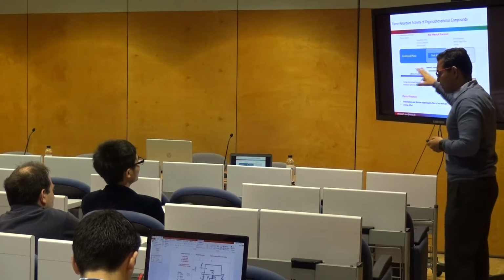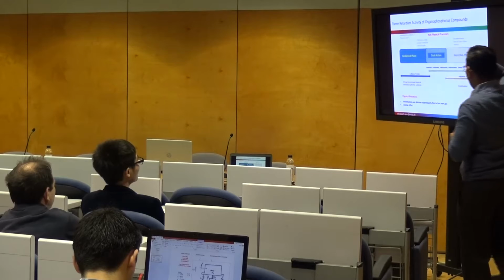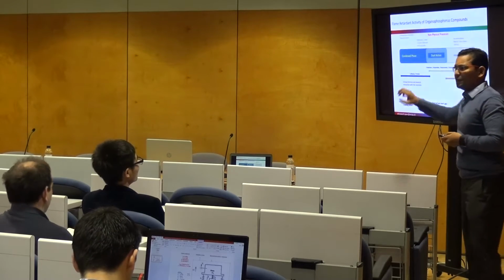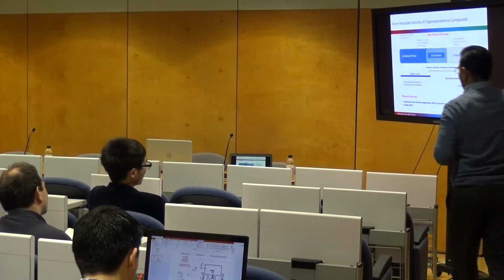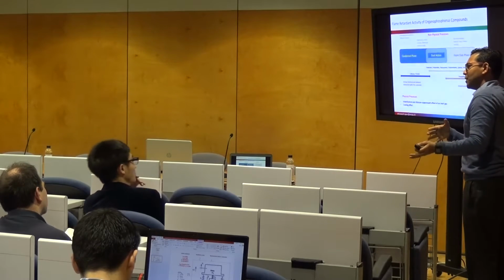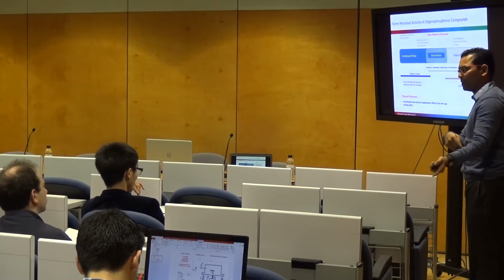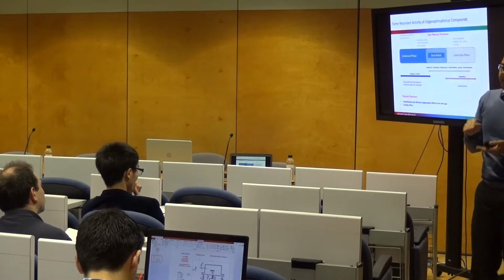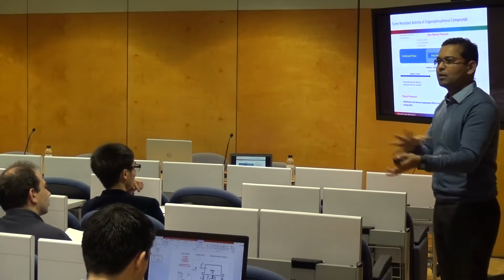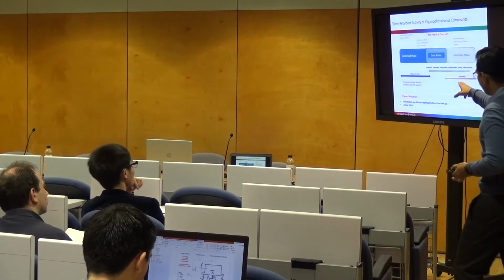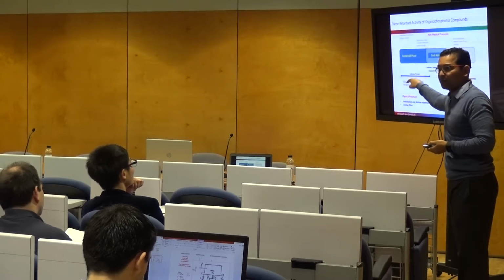So this is probably almost the last slide I'm trying to show you guys. So the condensed phase and gas phase, we talked about it in detail. What I try to tell people is that phosphorus as a flame retardant works in condensed or in gas phase depending on the polymer. You have to know, if you have cellulose, or wool, or a lot of hydroxy-containing polymer, the flame retardant, the phosphorus, will work primarily in condensed phase.